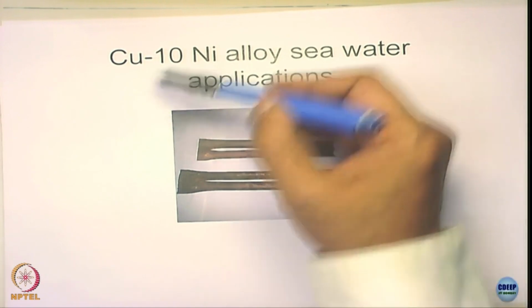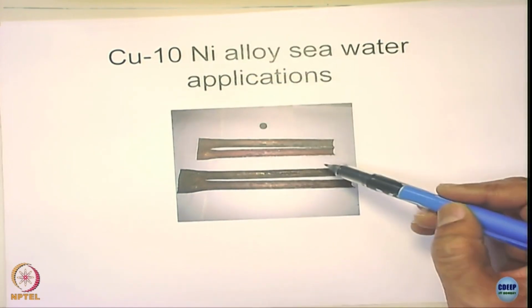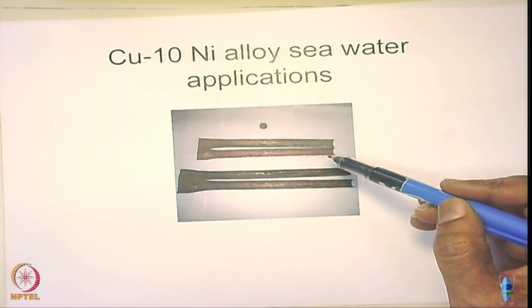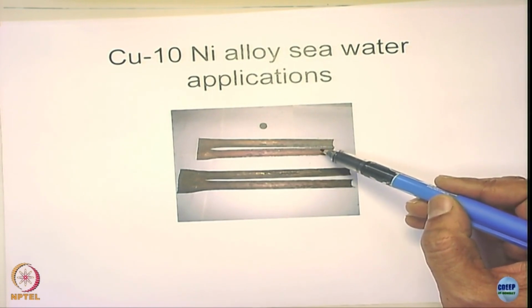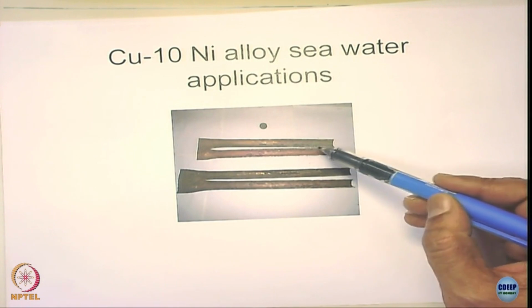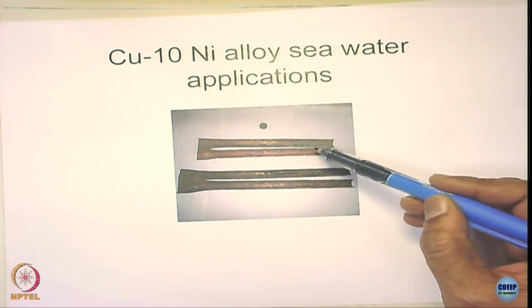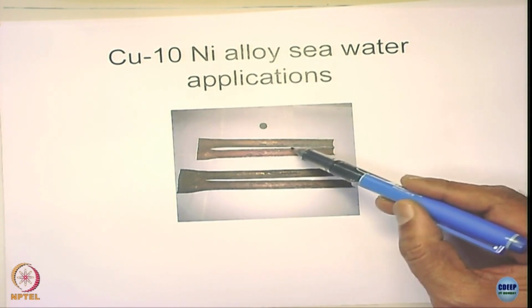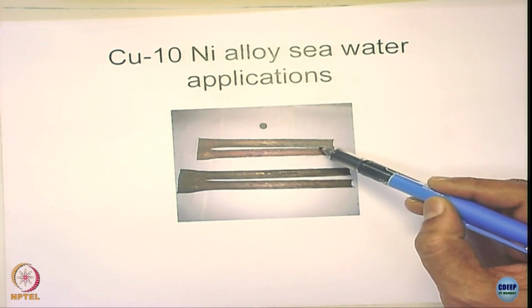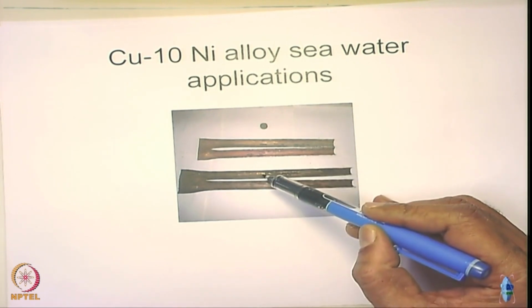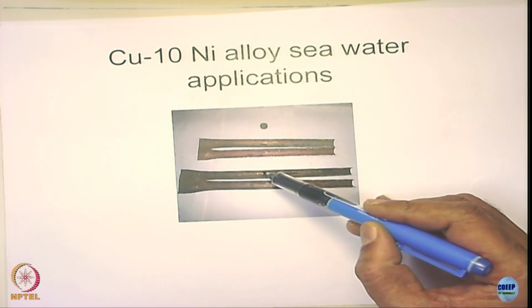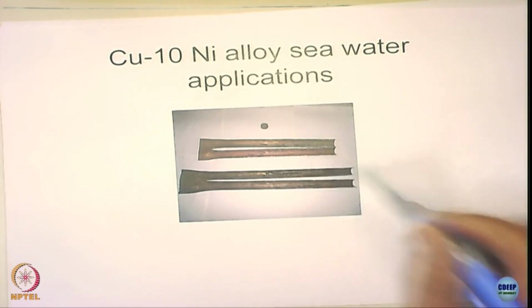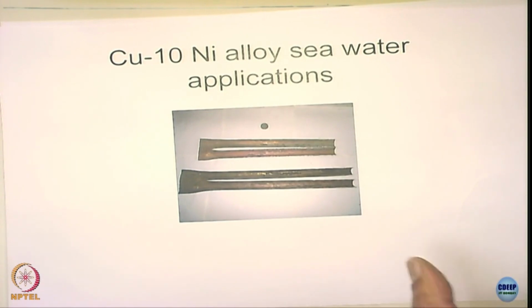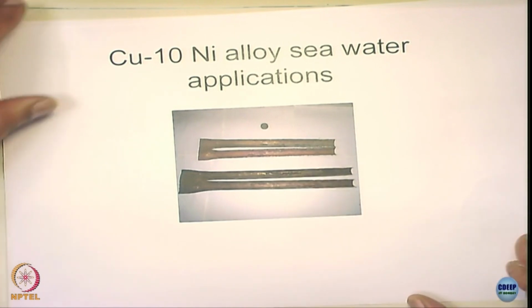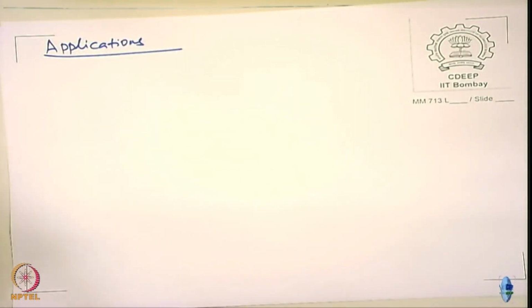This is a copper-nickel alloy in a seawater application in one of the refineries located in Mumbai, after about a couple of years. Seawater was passed through this heat exchanger. Now you see the coloration here. Look at this color, it is bright here, right? And the black thing that you see here is due to de-nickelification. The nickel came out of the surface and formed this. This is something which you normally see.